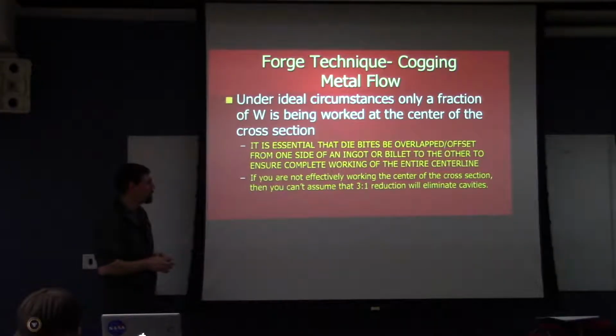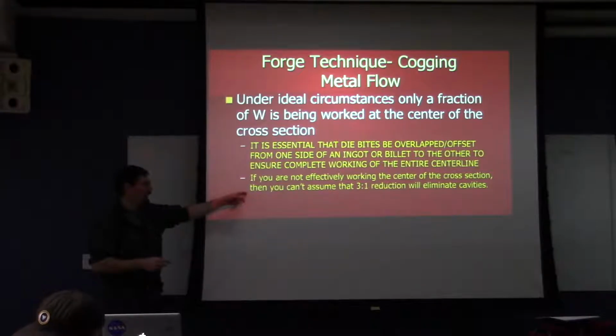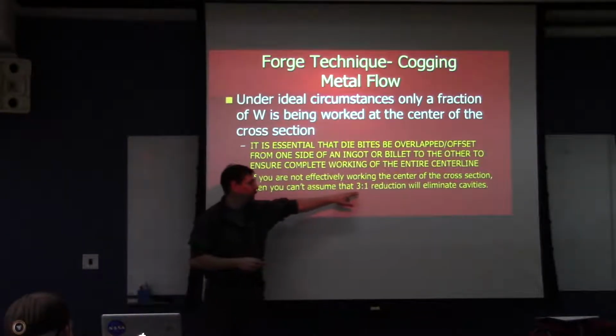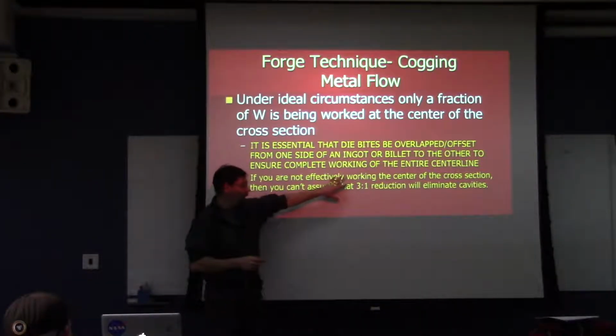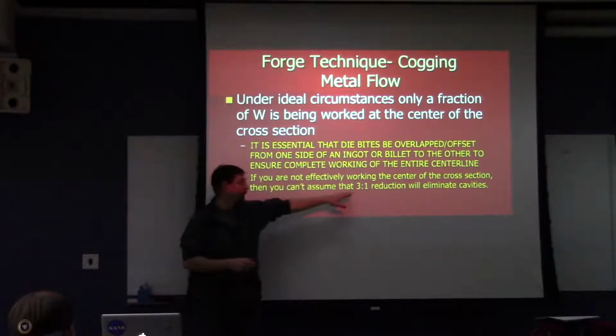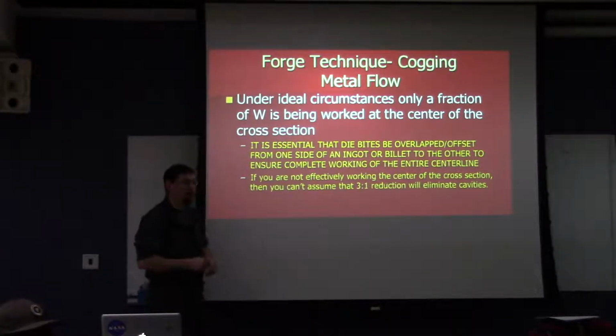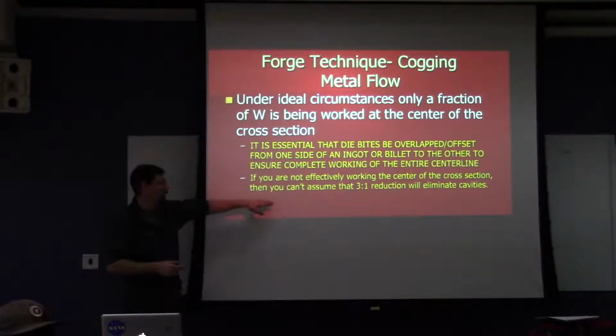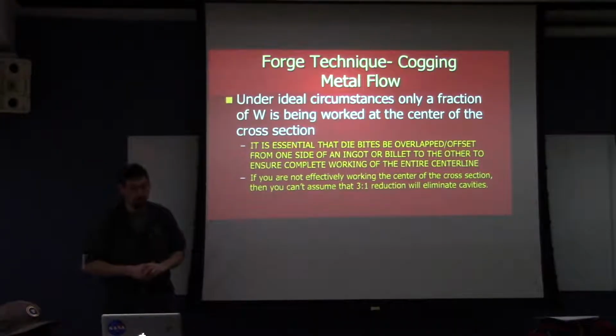So if we're not effectively working the cross-section, we can't assume that this 3-to-1 reduction will eliminate our cavities. If we're effectively doing that, then 3-to-1 is an excellent mathematical relationship. But if we're not working the center, then we can't use that 3-to-1.